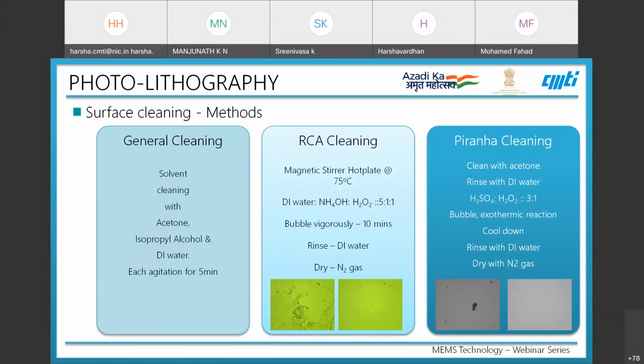There are basically three different methods for surface cleaning: general cleaning, RCA cleaning, and Piranha cleaning. In general cleaning, we use a solvent with acetone, isopropyl alcohol, and DI water, and agitate with each one of them for about 5 minutes. This is the most used step, and it is done for all substrates incoming for the photolithography process.